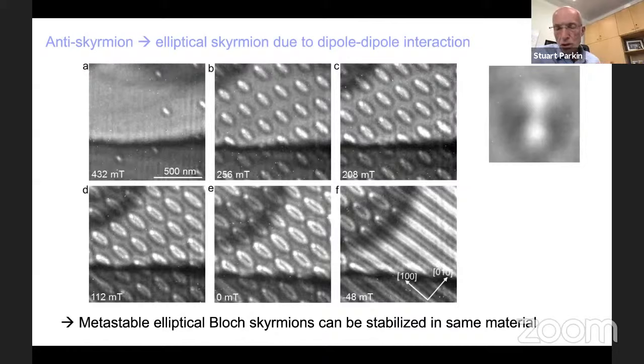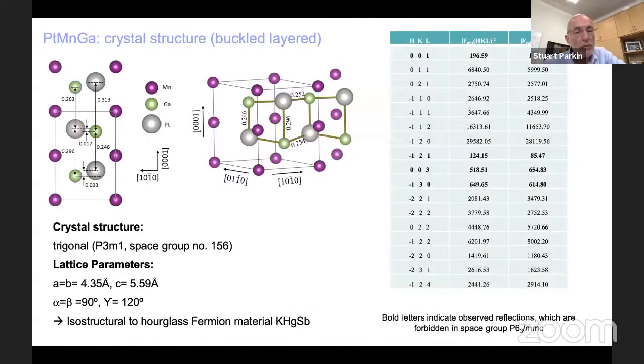Antiskyrmions are still restricted to this Heusler compound. But in the same Heusler compound, we can actually stabilize elliptical skyrmions. Again, this is dominated by dipole-dipole interactions. So they're no longer circular, as in the Bloch and Néel skyrmions previously seen, but these have an elliptical structure where the ellipse is oriented with its major axis along these two distinct crystal directions, these helical directions that I mentioned. So this is super interesting. And I wanted to finally mention that these chiral structures, these ground states, can now be found in many different systems. And one I can just briefly mention, again, is a crystal from Claudia's group, platinum, manganese, gallium.